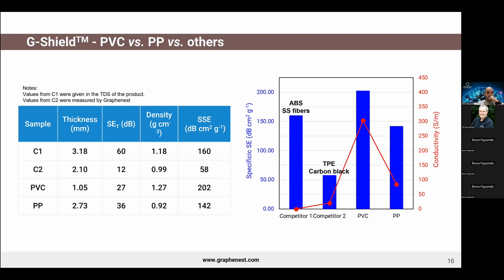Both G-Shield products were compared against commercial alternatives that use other conductive fillers and base materials. Namely, in this case, competitor one has a commercial product with ABS and stainless steel fibers as conductive filler, as well as a thermoplastic elastomer that has carbon black as conductive filler. The values from C1 were gathered from the TDS of the product, while the values from competitor 2 were measured here at Graphenest with the product in hand.